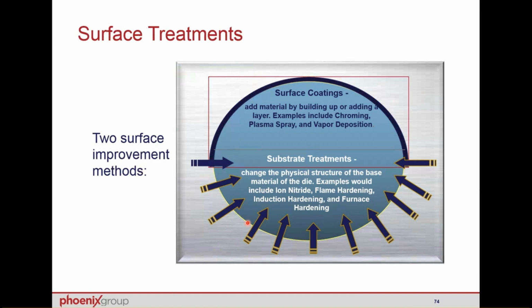Again, it might only be 6 to 8 thousandths of a depth, but it is a very, very hard, durable surface, and it gives them a little bit more wearability than a thin half-thousandths thick chrome layer. So it is a little bit more durable. Typically chrome plating, they can chrome the die and get it back to you in maybe as little as 24 to 36 hours.